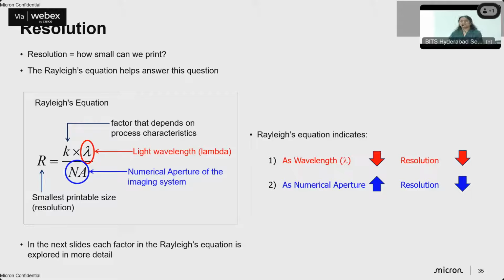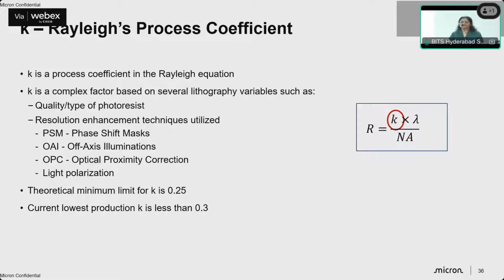So this is the equation that we go by, Rayleigh's equation, where, as we discussed, resolution is directly dependent on the wavelength of your exposure light and inversely dependent on the numerical aperture. R defines the resolution, how small a CD feature you are looking at. K here is a very interesting constant. It's the Rayleigh process constant, and a very intricate one, where it takes into effect your OPC, what kind of photoresist film you are using, what your target pattern is that you are trying to print, all of that. Theoretically, the lowest you can go with the K value is 0.25.